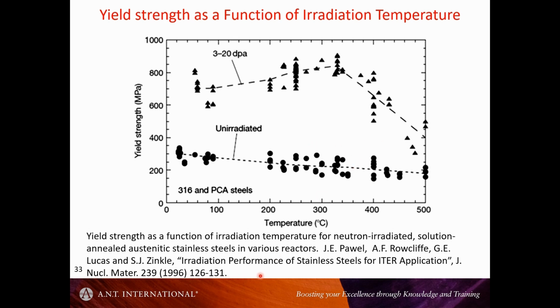And this is illustrated also in steels. Here's something I took from a review by Pawel and Zinkle. And basically, you see, as a function of temperature, using yield strength as a surrogate for the loop density, that at high temperatures the loop density becomes much lower, and the yield strength of the irradiated material approaches that of the unirradiated material, and that's because you have insufficient supersaturation at the higher temperatures to cause loop formation.